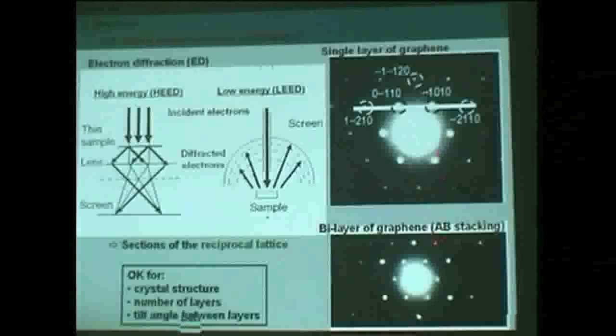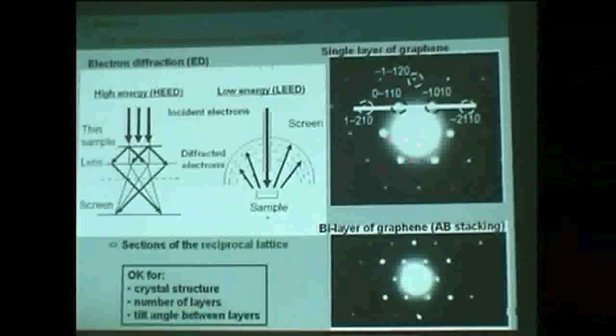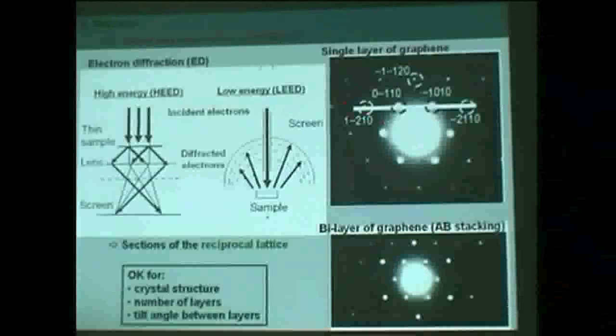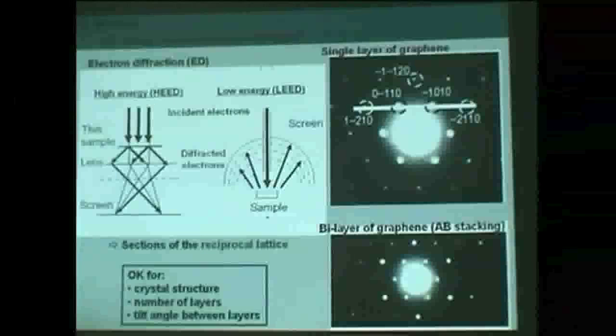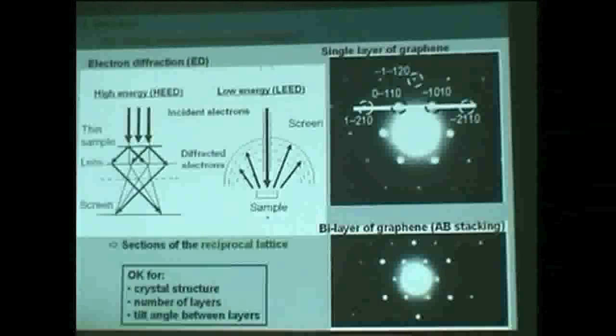This is for graphene. So if we make the Fourier transform of a graphene lattice, a hexagonal lattice, we also expect to get a reciprocal lattice which has hexagonal symmetry. So here you observe very nice hexagons, and this is what we expect for a single layer of graphene.